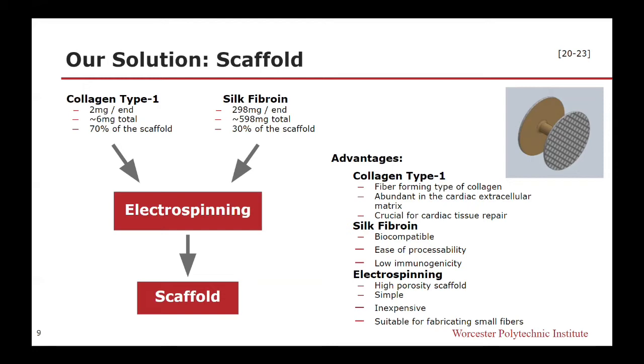Electrospinning is a process where high electric fields are applied to rotating cylinders, which align the fibers and create the scaffold. The anticipated tissue response of the scaffold is that it will be integrated and not encapsulated, as the porosity will help the cells grow into the three-dimensional scaffold. The materials of the scaffold will not evoke a foreign body response, as collagen is an abundant protein in the body, and the silk used in the scaffold will be boiled in sodium carbonate to remove sericin prior to use.